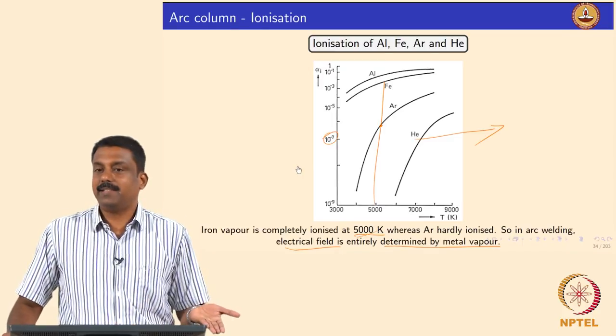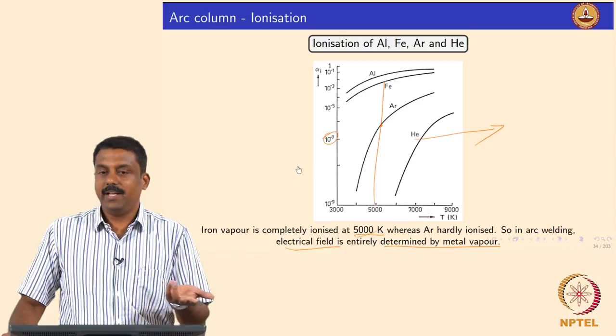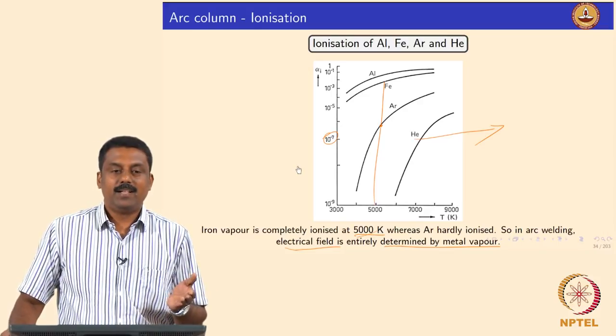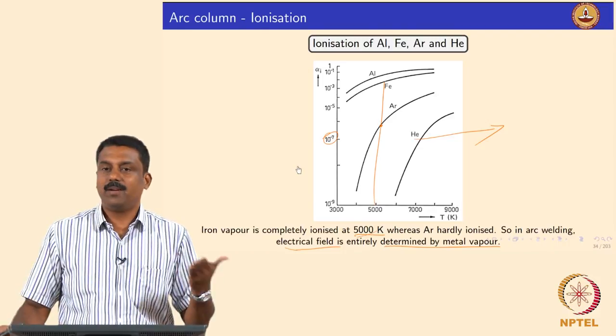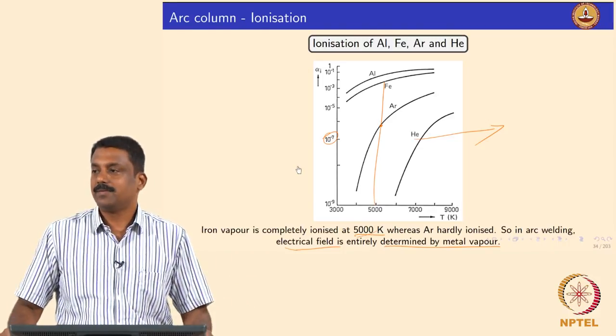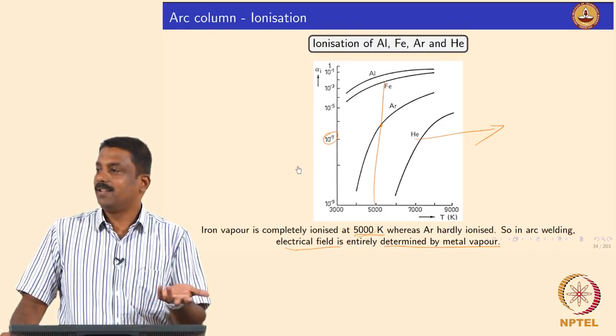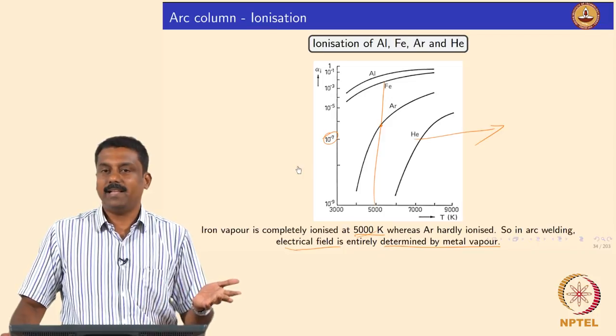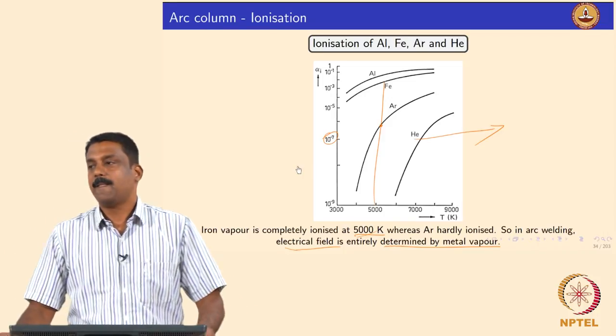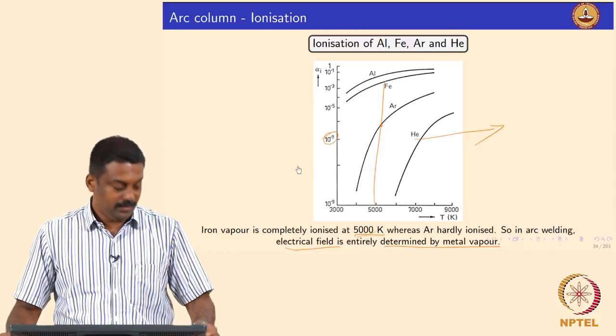Once the iron vapor ionizes, you have sustained discharge — the electrons and ions, the charge carriers, are transported from cathode to anode, so you strike and sustain an arc. It does not matter whether you create it only with argon or helium; as long as you have a gas — in this case metal vapor — the arc is sustained.